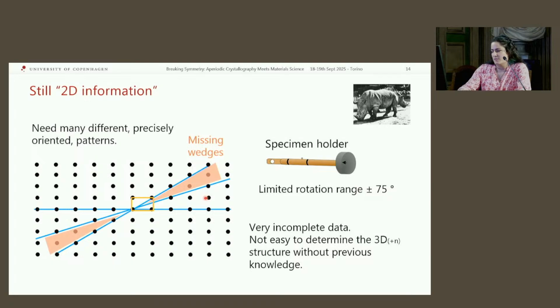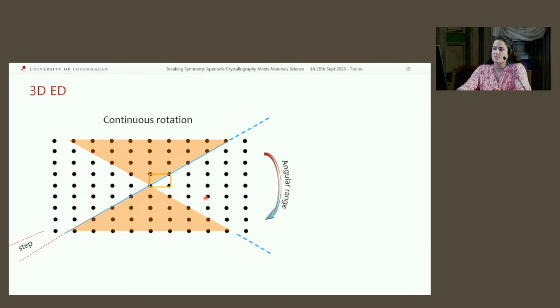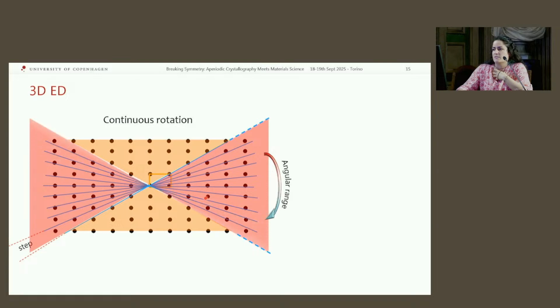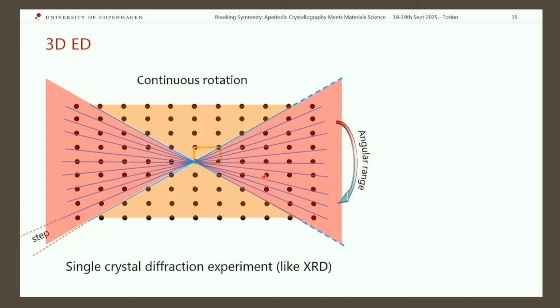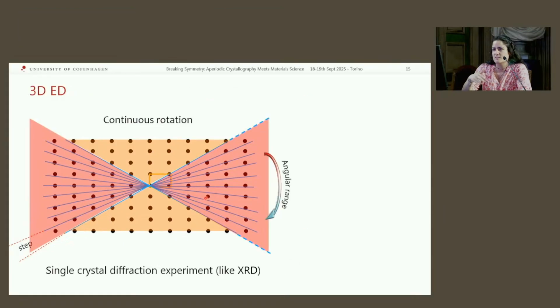We need prior knowledge. So the natural progression of this experimental approach would be to collect as much as possible of the reciprocal space with continuous rotation of our sample. In this case, we can sample a much larger region with fine steps and get more complete data. Those of you that are X-ray crystallographers will be unimpressed because that's what we do with X-ray diffraction all the time, right? We rotate the crystal in many directions and get more than complete data. But this was not so easy to do with electron diffraction so far,